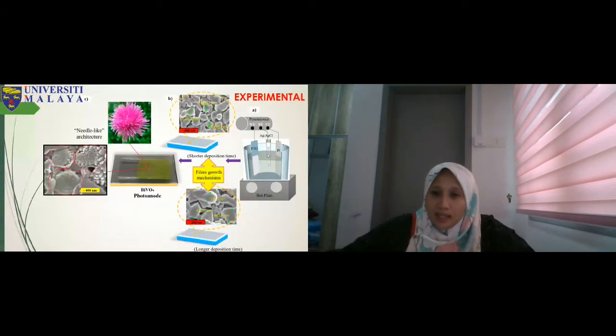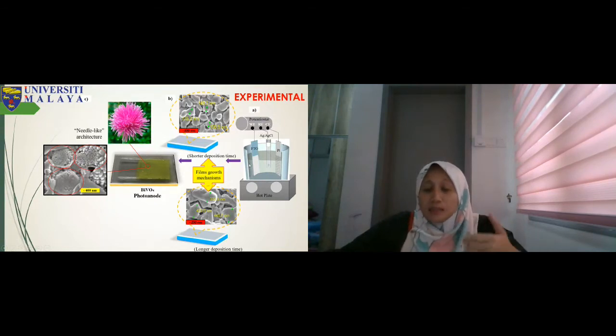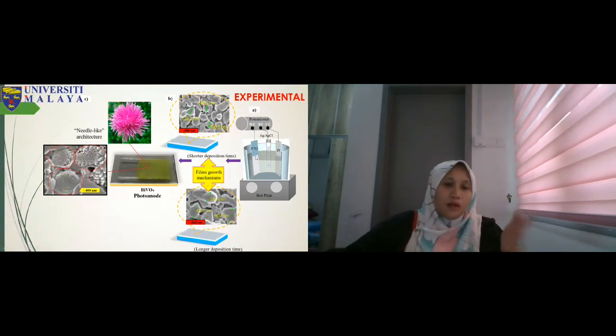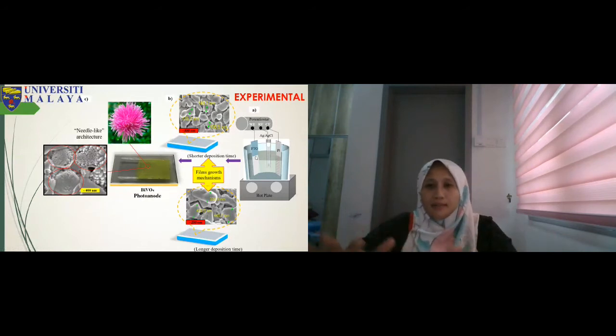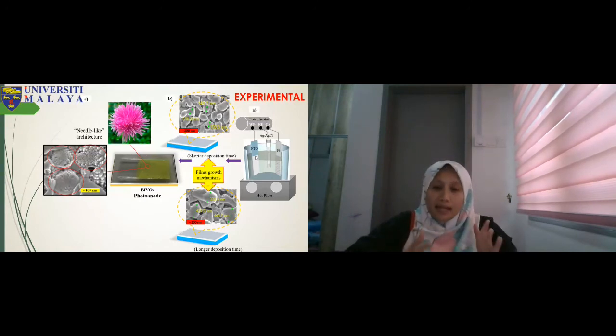This is the three-electrode setup I made. This is my conductive material, this one I use as the Ag/AgCl reference, and this is my platinum. In order to deposit our material, I use a hot plate with a temperature of around 70 degrees. I varied the deposition time from 1 minute, the shortest, to the longest time of 9 minutes. So I used five variable times, because we want to check the optimum one first. Then we deposit here on the FTO.